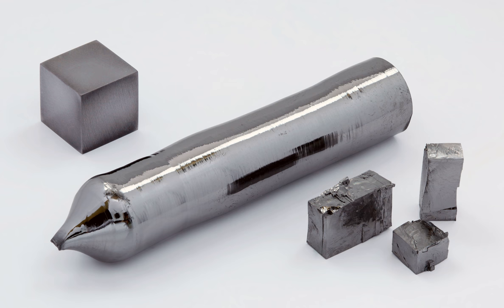This simple procedure allows the removal of most metal-containing impurities, e.g. iron, manganese, titanium, zirconium, which remain in the aqueous phase in the form of their fluorides and other complexes. Separation of the tantalum from niobium is then achieved by lowering the ionic strength of the acid mixture, which causes the niobium to dissolve in the aqueous phase. It is proposed that the oxyfluoride H2[NbOF5] is formed under these conditions.